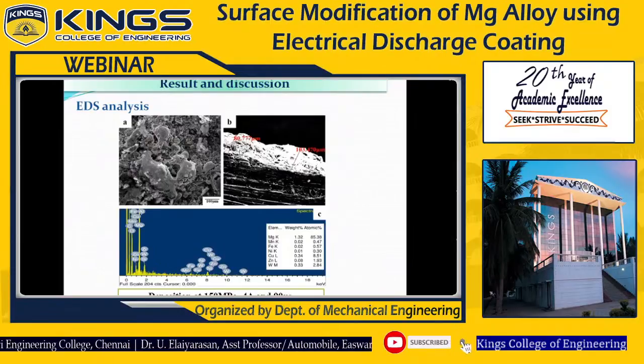Here is also the EDS analysis of the surface deposited at 150 volts, 4 amps and 90 microseconds. Some of the electrode materials present over the surface of the workpiece are confirmed by the EDS analysis. It is a very important study in this research. Magnesium, manganese, iron, nickel, copper, zinc and tungsten are also present in the deposited surface.